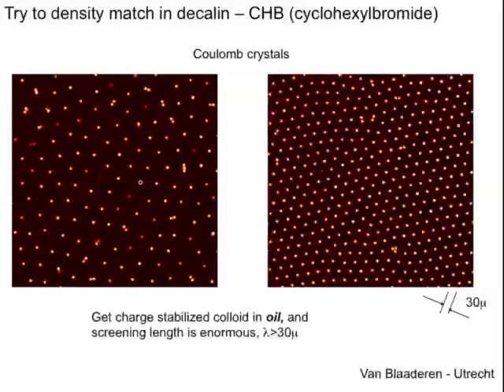Now the problem was, the groups that were trying this, they tried very hard to get rid of the electrostatics. Sometimes they could, and sometimes they couldn't. They were after hard spheres, after all. Turns out, Coulomb crystals were known before this in colloids. They're fairly easy to make in a water system, instead of in cyclohexylbromide, which is what this was in. So some of this was done by the group in Utrecht, and I was at Princeton at the time, and we had the right machinery to do dielectric spectroscopy on these things to see what's wrong. And the problem was, sometimes they would see this effect, and sometimes they wouldn't.